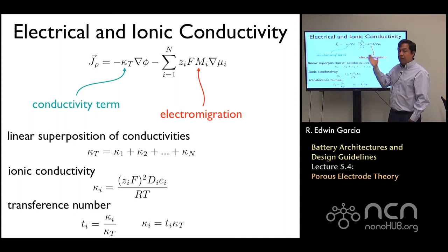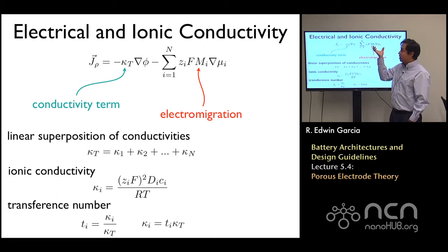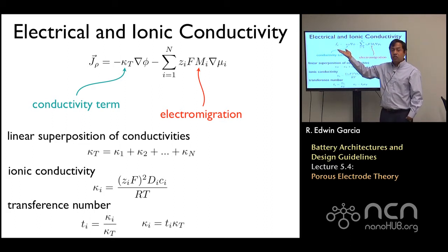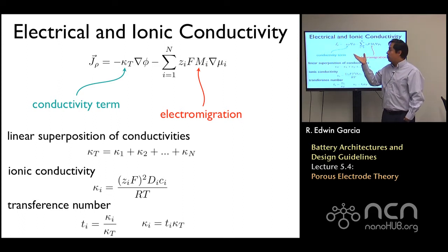So for an electrically charged system, you can see how this term over here, even if you have only an electrical potential, that was enough to induce a mass flux in one direction and completely change your charge flux in the medium where you have an ionic species. Now, this would allow us to describe explicitly the mass transport in a general electrochemical system.